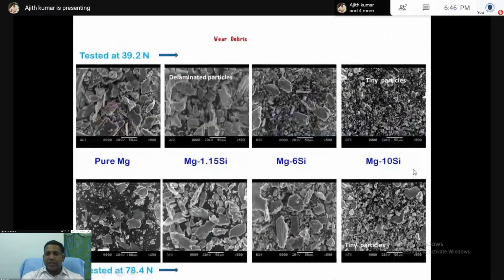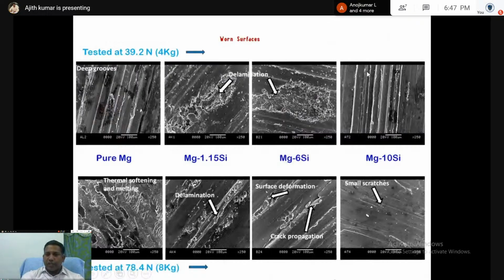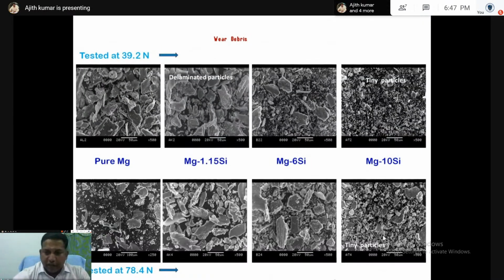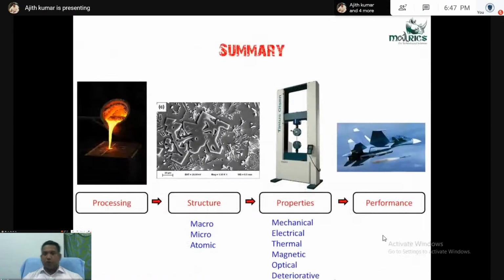And in the case of Mg-10Si, there are very small tiny particles. And in the SEM image, the line scratches are very small. Because of the hard Mg2Si particles present in the matrix, we are not able to make a deep groove. That's why very small scratches are there, because it is a barrier. That Mg2Si acts as a barrier for wear. So that we can confirm using wear debris. So with this talk, we understood that.